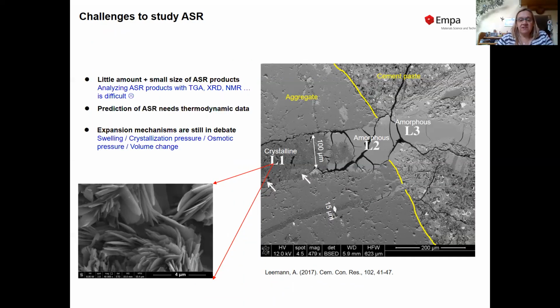If we look at it as a function of distance, we see different hydrates formed. We see a crystalline one, we see some amorphous. And if we go out from the aggregate to the cement paste, we also start to see that it intermixes with the CSH. There's a number of open questions. One of them is that they are difficult to study because they are so small in size. We didn't have thermodynamic data until very recently. There's a lot of question on the expansion mechanism.